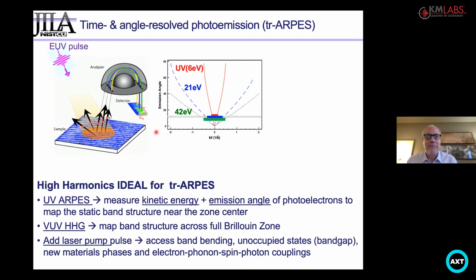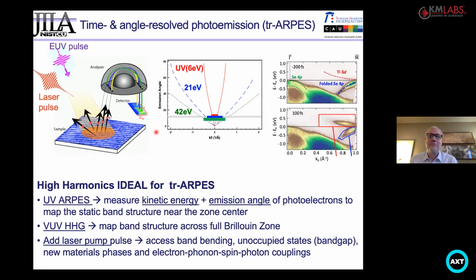And if you add a pump pulse to do pump probe spectroscopy, you can access, for example, the unoccupied states of a material, or how the band structure of a material changes as it goes through a phase transition. Also, how electrons, phonons, and spins are coupled in a material. So there's a rich variety of information that you can get by doing pump probe studies with angle resolved photoemission. And that's on top of the large body of work in ARPES done in a non-time resolved fashion.